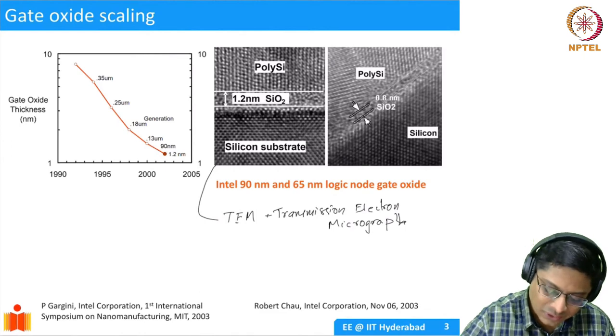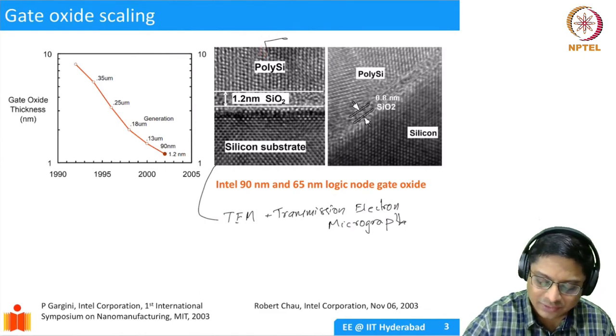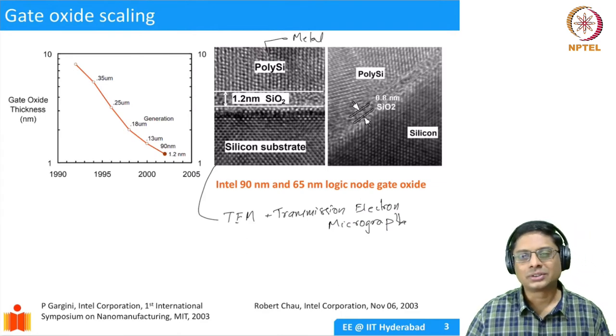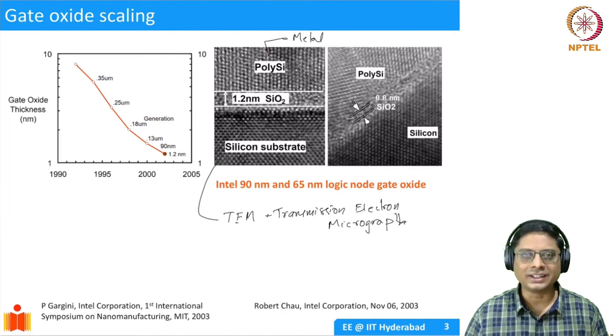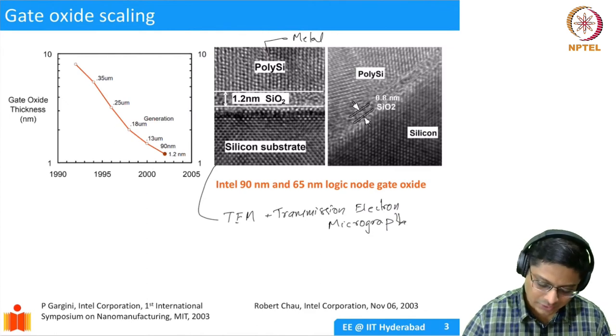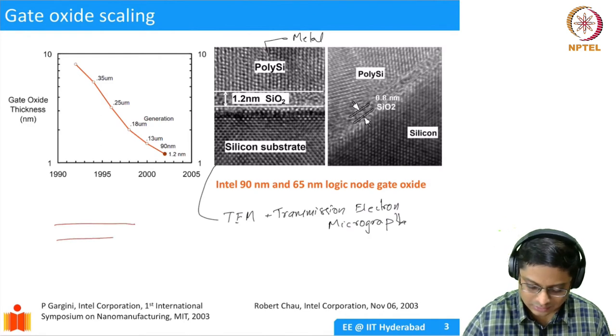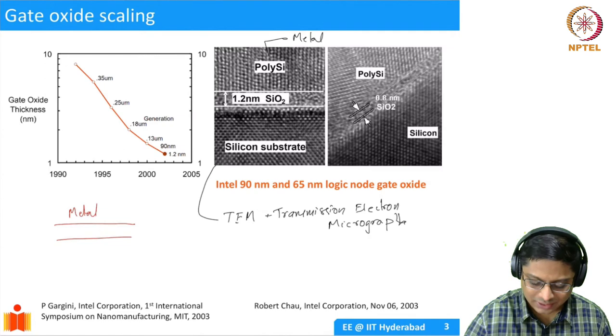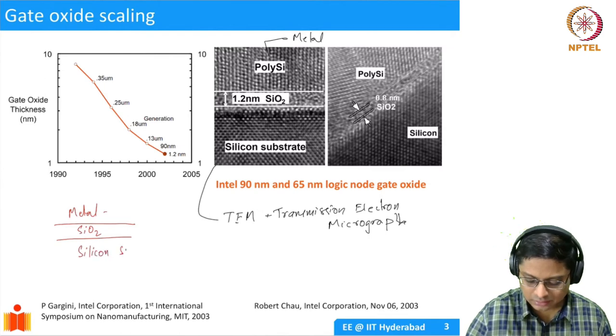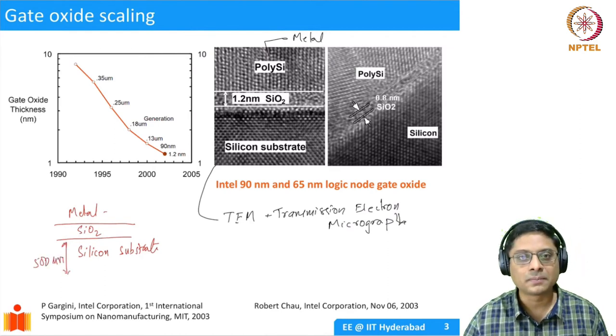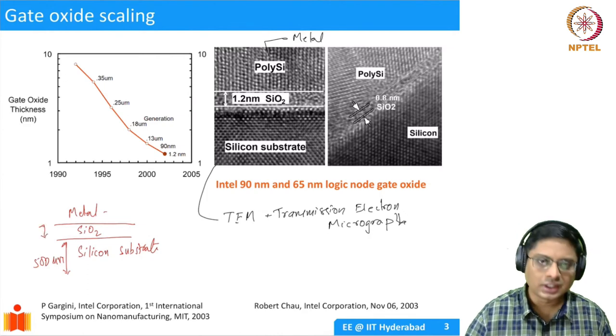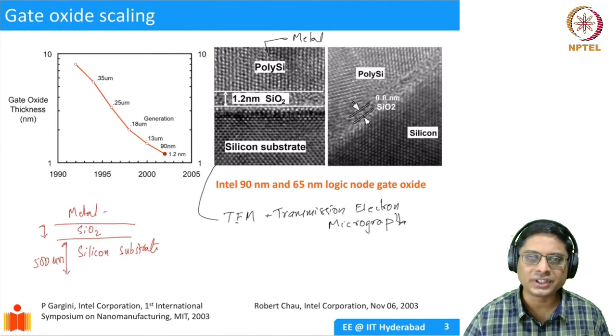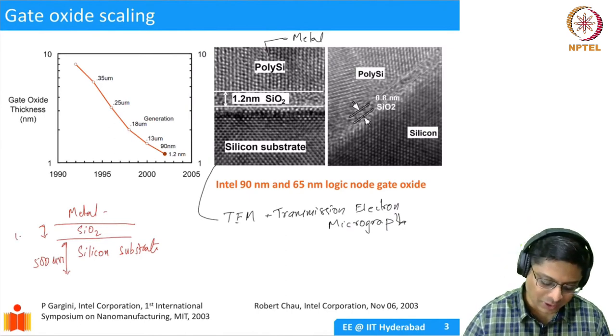On top of it, in this case, instead of a metal, we are using polysilicon. In the 1970s and 80s, we were using aluminum as a metal. So what does our MOS capacitor consist of? You have the metal, which has some thickness, then silicon dioxide, and then the silicon substrate at the bottom. The substrate would be something like 500 microns thick, half a millimeter thick. Whereas the oxide, in the early 90s, was 10 nanometers or 8 nanometers. But by 2003, it was already 1.2 nanometers.